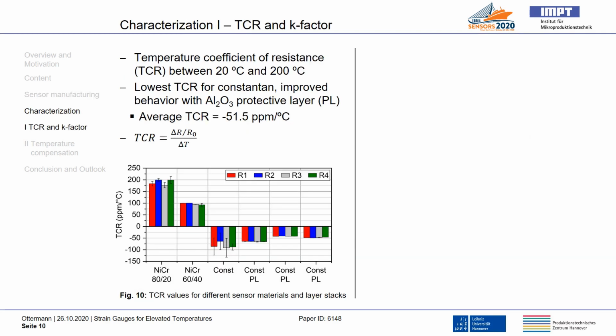The characterization starts with a comparison of the different sensor materials regarding the TCR up to 200 degrees Celsius. The aim is to find the material with the lowest TCR amount to simplify the temperature compensation afterwards. The TCR is calculated by the resistance change, the initial resistance, and the temperature change. In Figure 10, the TCR values for single strain gauges R1 to R4 are shown. In the first 3 columns, we can see the results for the 3 sensor materials. The lowest TCR amount could be achieved for the constantan layer, even though the standard deviations were very high.